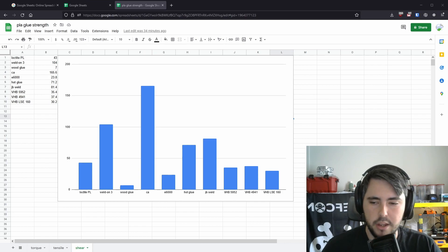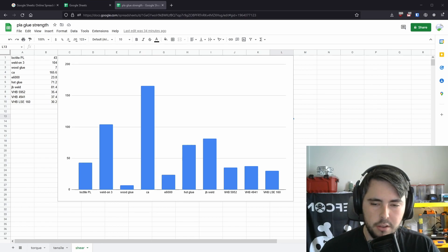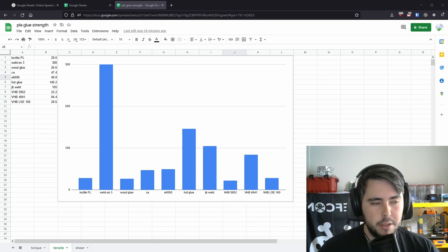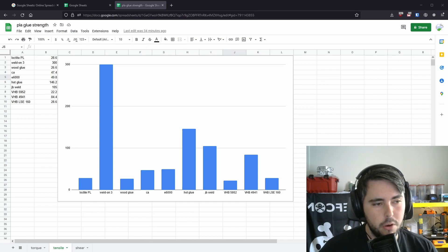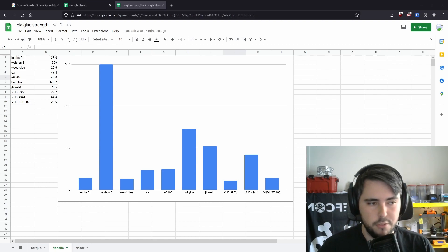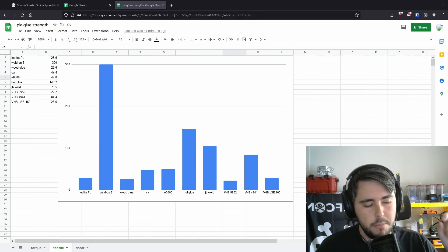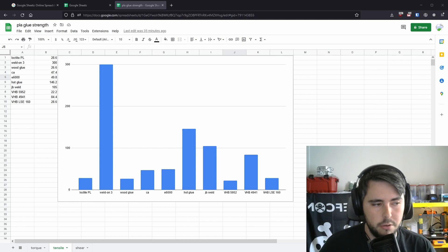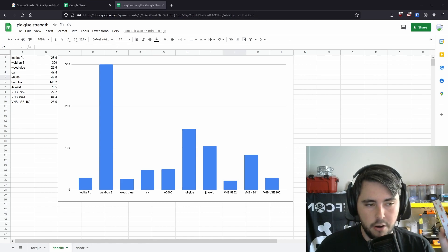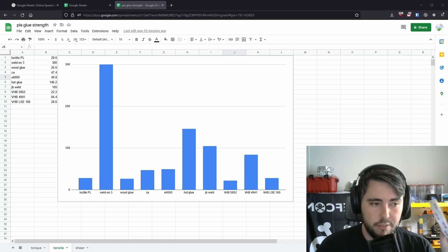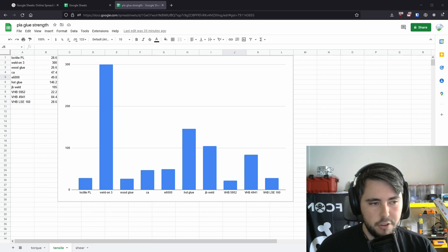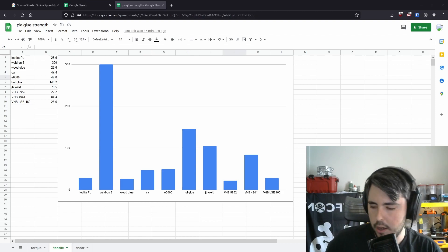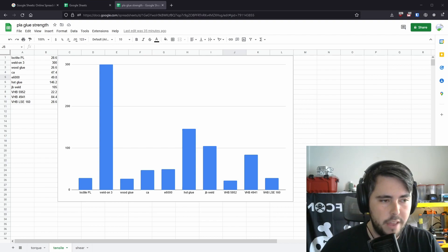Talking about the double-sided tape, it looks like VHB 4941 is the winner. So here it's very closely the winner. But if we look at the tensile strength, it is definitely the strongest out of all of them. And I really like to see that because if we look at the tests, 5952 broke on the foam carrier and not on the adhesive. Now, what that means is when you go to remove the adhesive from the floor, the wall, the desk, whatever you've stuck it to, 5952 will tear across that foam and it will leave adhesive residue on what it's stuck to. Whereas with 4941, because it failed on the adhesive and not on the carrier, that means it'll come off cleanly. It's still annoying to get off of whatever it's stuck to, don't get me wrong, but it'll come off cleaner than 5952. So this is the VHB that I would recommend, the gray tape with the white backing paper. Most listings on Amazon and stuff do list the 4941 as well. So just look for that.